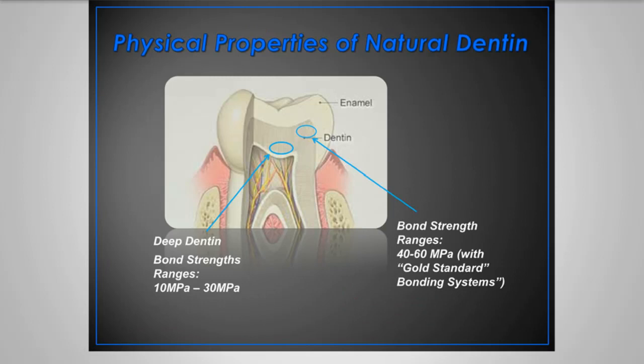So again, physical properties of natural tooth, we have good bond strength to superficial dentin and enamel at about 40 to 60 megapascals. These are gold standard areas for bonding. Now, deep inside the tooth, like I just showed you on the SEM, bond strengths are significantly lower at 10 to 30 megapascals. We have a lot more risk of sensitivity and or pulling our bonding agent off the pulpal floors. And this is where we're going to find postoperative sensitivity, microleakage, and recurrent decay. So if we didn't have a problem with bonding agents in these areas, I wouldn't be recommending glass ionomer.